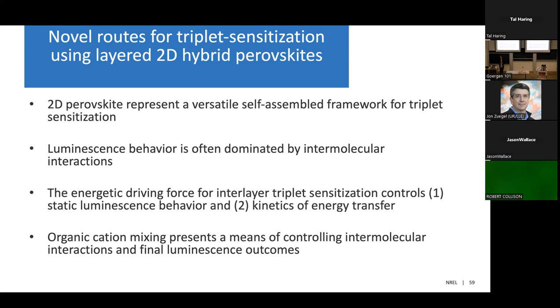What we've found through our work is that the luminescence behavior in these materials is often dominated by intermolecular interactions. And we can tune the energetic driving force for the triplet transfer at this interface, and that controls both the static luminescence spectra, as well as the kinetics of energy transfer. And finally, I'm really excited about organic cation mixing as a strategy for controlling intermolecular interactions in order to get wide color tunability in these materials.